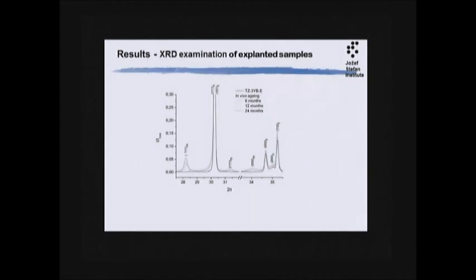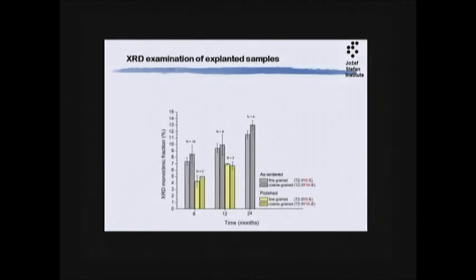Okay, so these are the X-rays, boring stuff, but we have a lot of peaks. We have tetragonal, we have monoclinic, tetragonal, cubic, we have distorted tetragonal and distorted cubic. It's a mess. But what's important is this result. After the 6 months, we got quite a serious amount of the monoclinic on the surface of the specimens. After 1 year, that goes a little bit up.